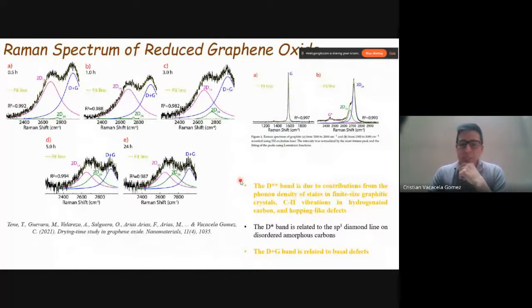Now, the interesting thing here is that in amorphous carbons, as we mentioned before, the D band appears due to the finite size of graphite crystals or different vibrations, and the D star band appears due to the sp3 diamond line, etc. But when you observe in the Raman spectrum the presence of the D star band plus the presence of the D plus G band, you are talking only about the effects on your graphene oxide or reduced graphene oxide sample. It's not really connected with all these other contributions. This is because we are not hydrogenating our graphene oxide, so it's only connected with the effect of defects, as in the previous comment.